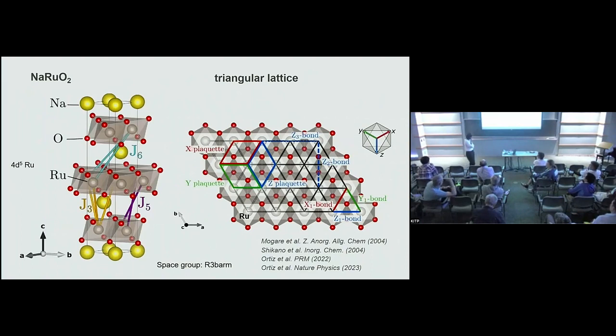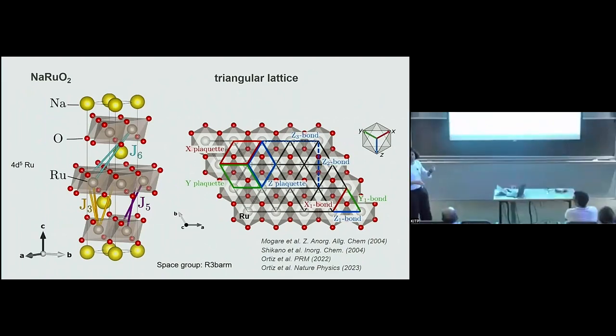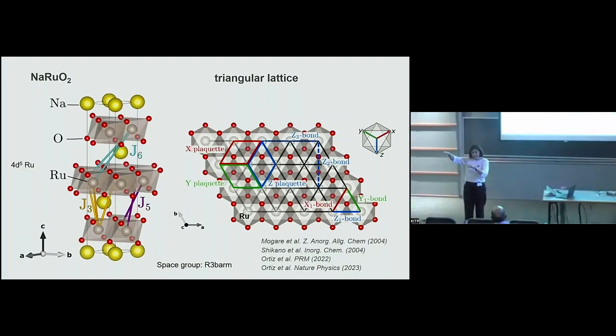Yeah, exactly. We were discussing the susceptibility with Stephen, because I don't have the picture of it here. What is interesting is what kind of Curie-Weiss behavior you have in this sodium ruthenate. Stephen goes up to 300 Kelvin, and then at low temperatures, he gets a rising up due to some magnetic impurities. Leon has looked into that in more detail than me. But for the Curie-Weiss, we would need higher temperatures to really get a good fit, because we have to extract this term here, and this we couldn't test.